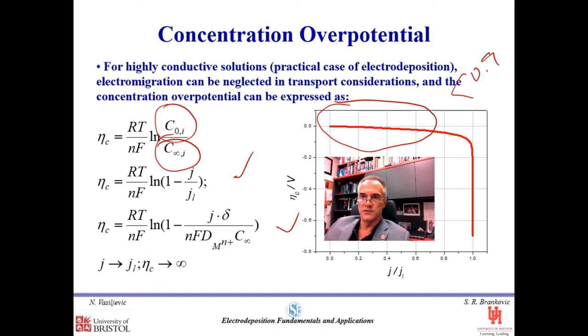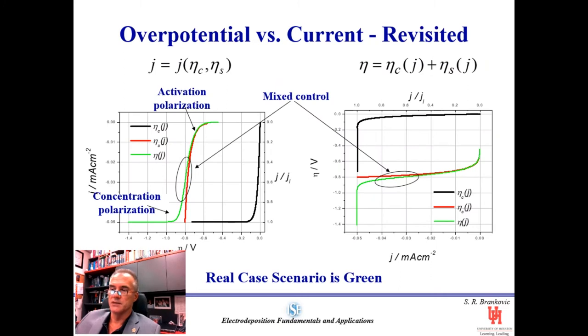However, when the ratio between the deposition current density and the limiting one approaches one, which is basically above 0.9, the contribution of the concentration polarization becomes the dominant contribution to the observed overpotential. And obviously, trying to reach the limiting current density, the overpotential mathematically goes to infinity. In reality, the overpotential versus current density relation is shown with the green line, which is basically a combination of both contributions, activation polarization related to the kinetics of the electrodeposition, and concentration polarization related to the transport. In either way, we see a little bit different shape than each of these curves represents, which is related to their contributions, each dominating a different part of the overpotential scale.